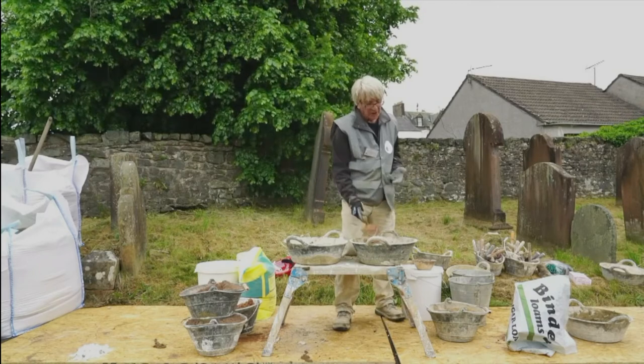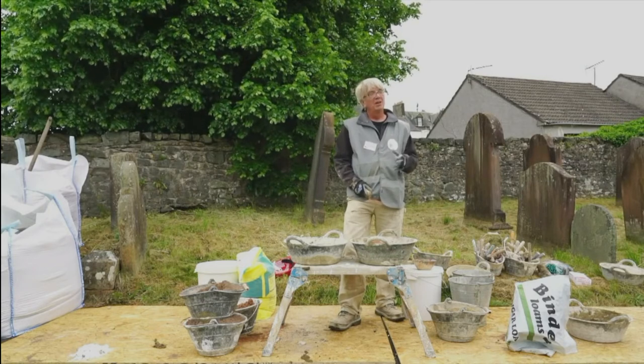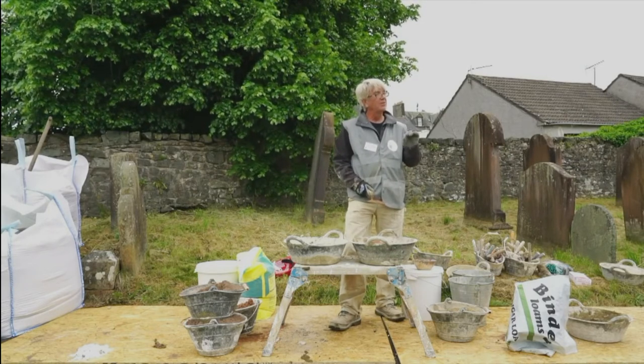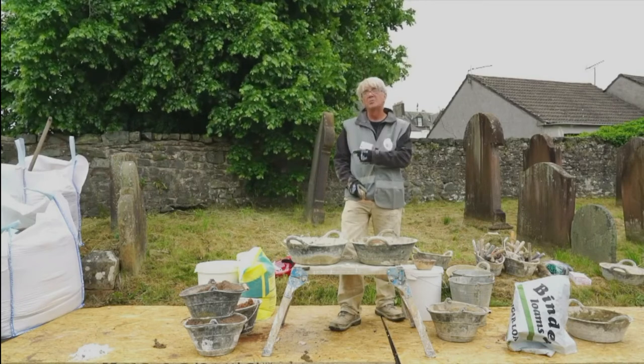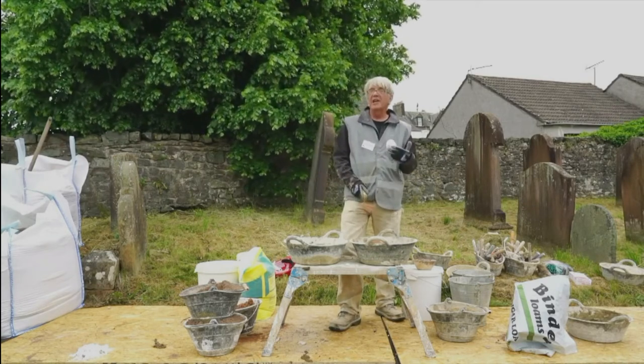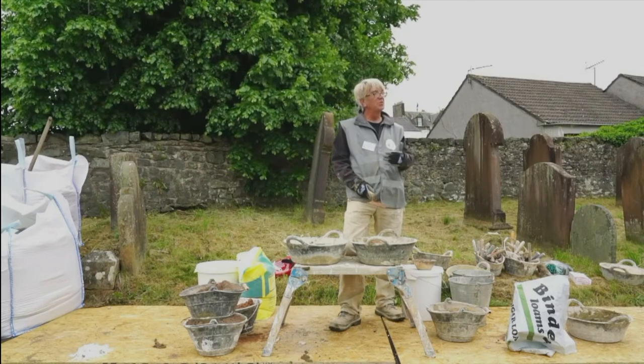And then we're thinking, well, actually, when you think about it, at least some of the slaking in here is being done by steam, not by water. Although you can only slake with steam when it's ground to a fine powder. The dry hydrate that we get from Tarmac or wherever you buy in the builder's merchants, dry hydrated builder's lime or whatever they call it, they slake that with steam. I've spoken to Tarmac. They grind it to a powder and they slake it with steam.